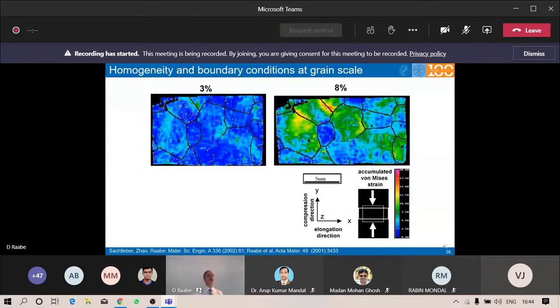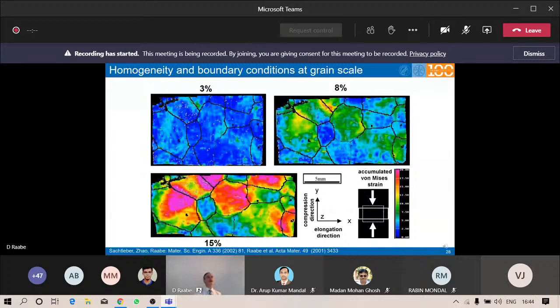have undergone a deformation beyond 20% locally, while this very hard rotated Gauss grain in the center, this little blue grain, has deformed not more than 2 or 3%, while the entire sample was loaded 15%. So that shows you from a very trivial high purity aluminum sample how enormously inhomogeneous such a deformation can be. And that is just the 20-year-old simulation result that we achieved by finite element calculations, by crystal plasticity finite elements.